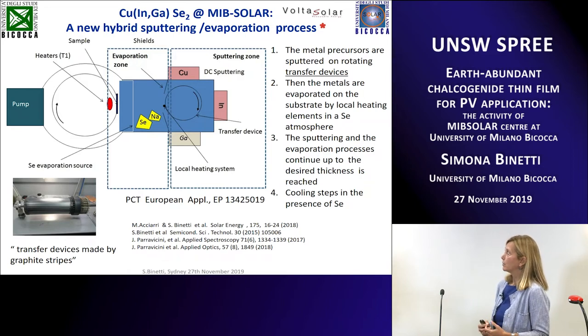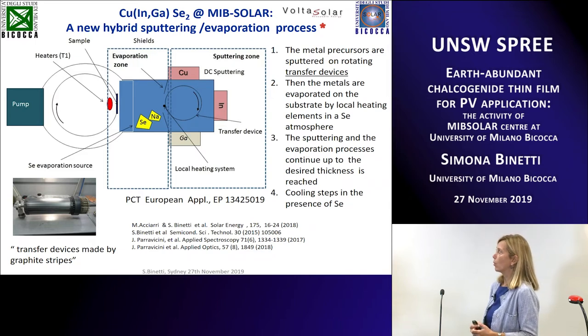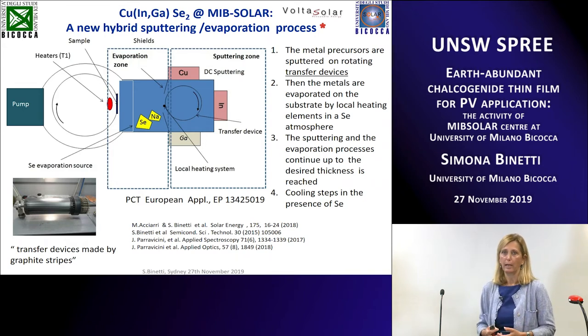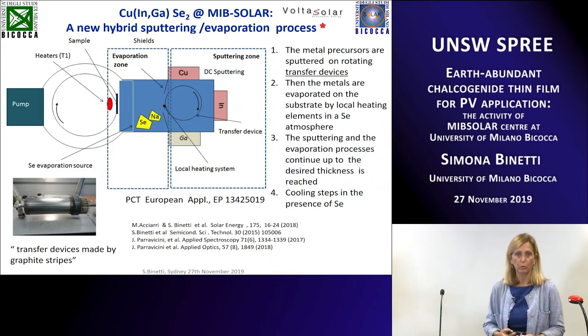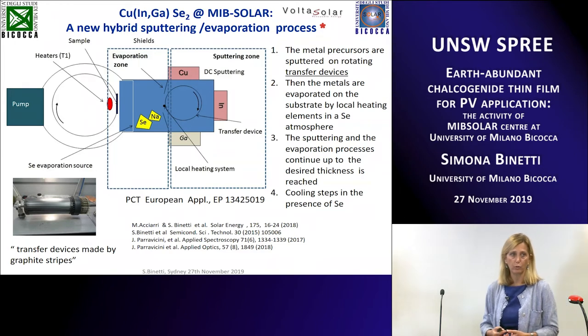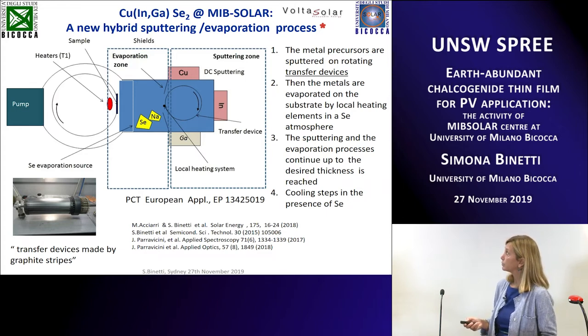Then the sputtering and evaporation process can go on until the right thickness is reached, and then we have a cooling step, always in the presence of selenium. If you don't use a substrate like soda lime glass, we can introduce sodium by evaporation from a sodium fluoride source. And you can see that this can be done in a roll-to-roll configuration, and we will see it much more clearly in the industrial line that I will show later.